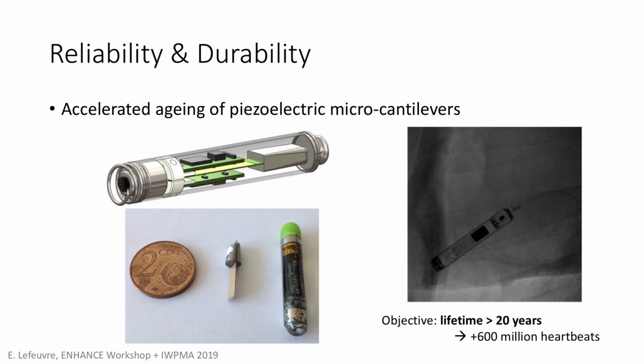Let's say if you consider 3 oscillations, 4 oscillations, 5. It depends on the way you extract the energy from the cantilever. If you can extract the energy very efficiently, you will have only a few oscillations, 2 or 3, 4. But if you can't extract the energy very efficiently, you will have a lot of oscillations after each heartbeat. And this will increase the aging of the system.